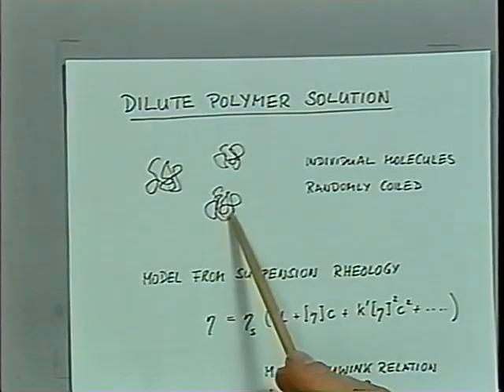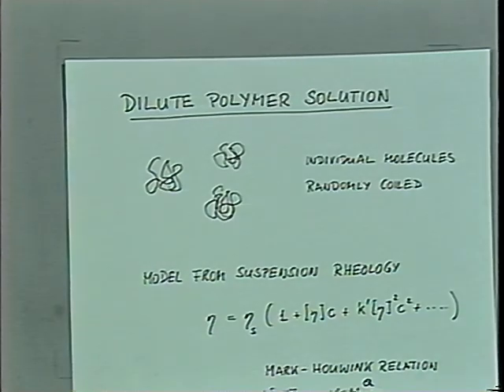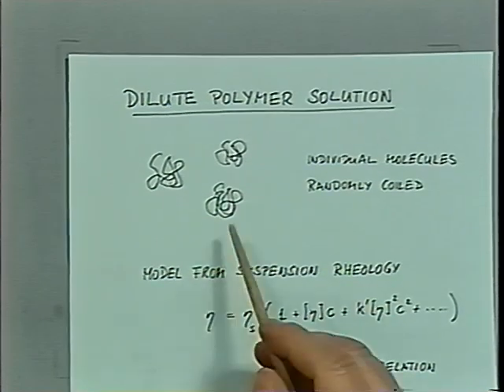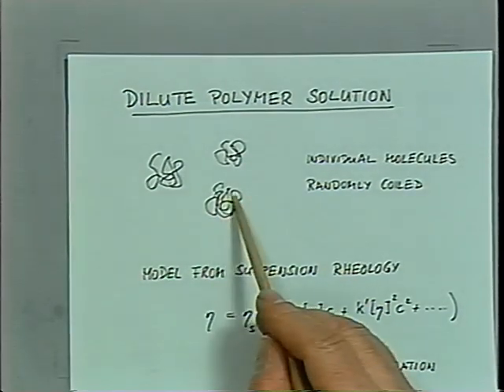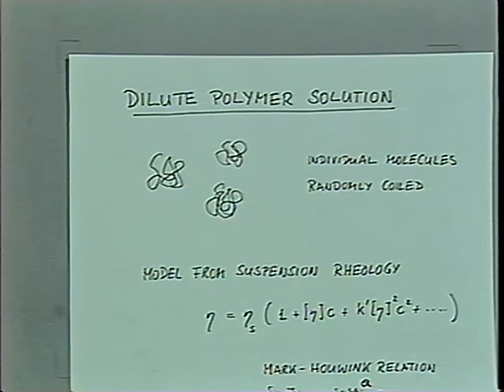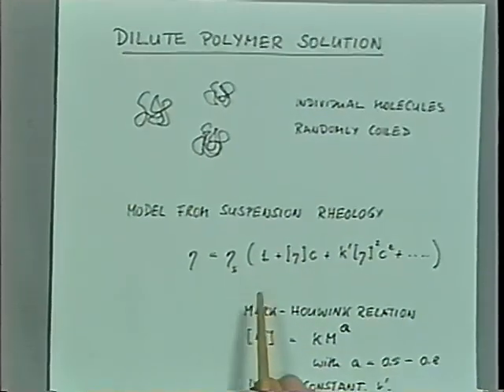So let's look at the polymer solution in the very dilute state. That's a system where the polymeric molecules are separately floating around in the solvent. They are separate entities. Like here, you could model them with little balls. In fact, Einstein was interested in the viscosity of a system like that when he derived the model for the viscosity of a polymer suspension. So in dilute polymer solutions, we treat the molecules as separate entities which are floating around, and in shear flow, those separate entities will increase the viscosity.